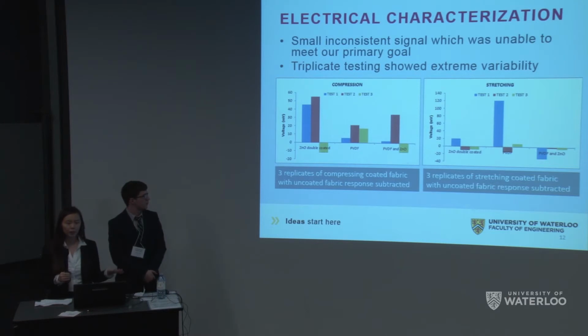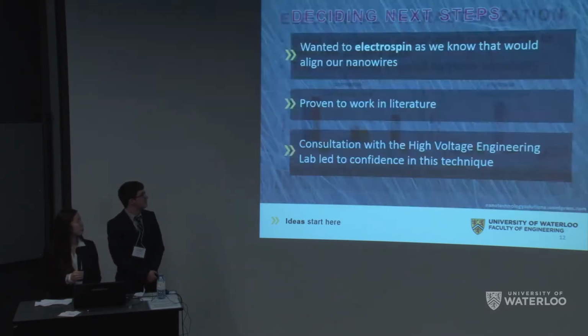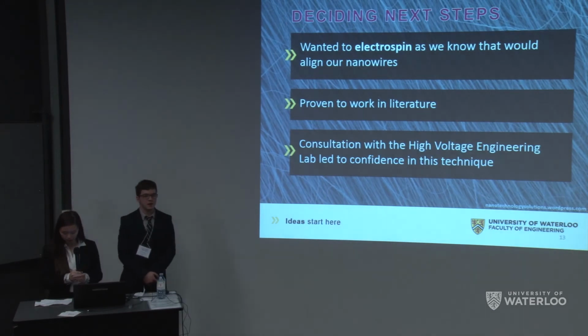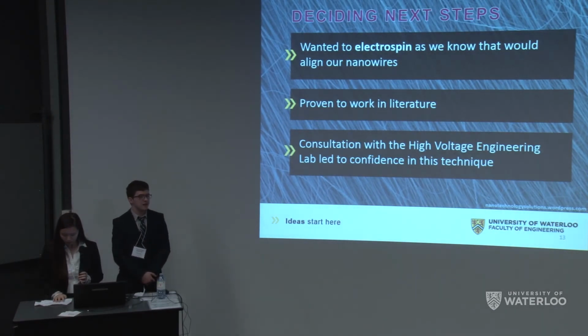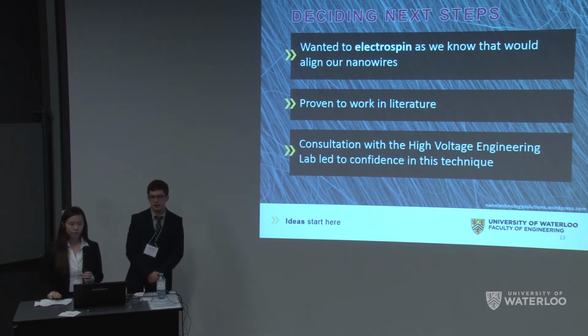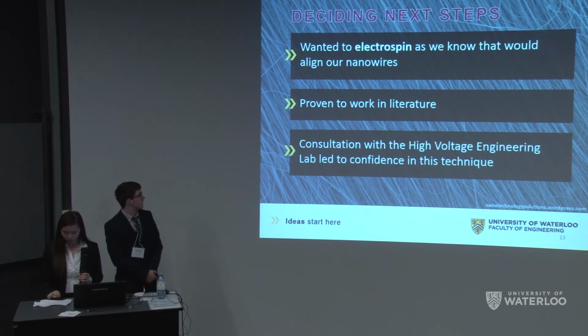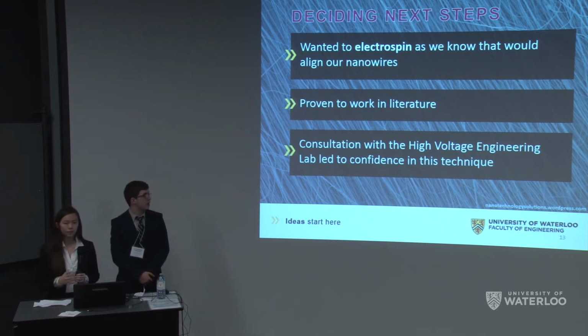So then we realized, okay, it's the deposition method that's at fault, and we were definitely not going to achieve the results we wanted if we continued with this kind of deposition method. So in order to make a film that we feel would meet our requirements, we decided that we would look to electrospinning as our method. So electrospinning we believe would work because you apply a high electric field which would allow you to align and evenly distribute your nanowires. We saw that it was proven to work in literature for similar applications, and we had consultation with the high voltage engineering lab, which led to confidence that this technique would work.